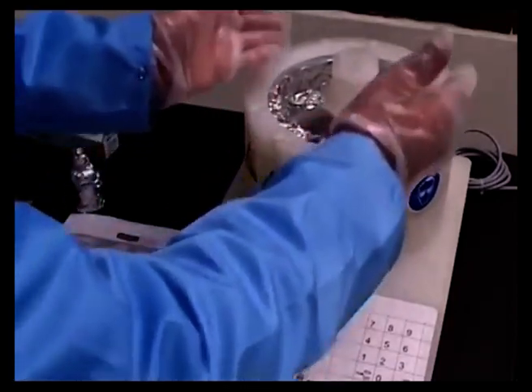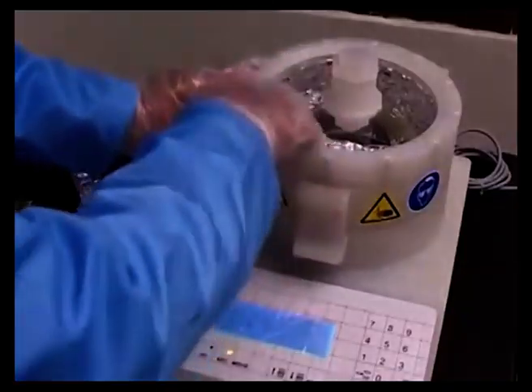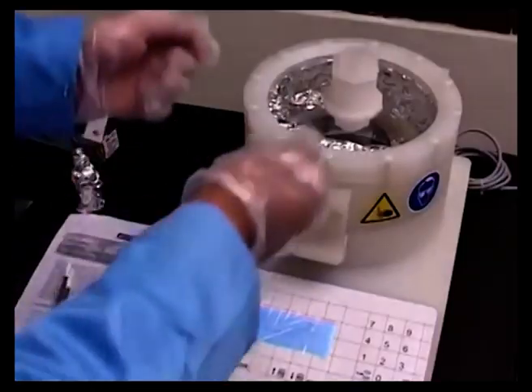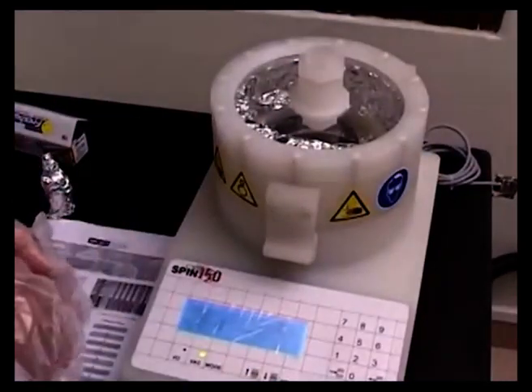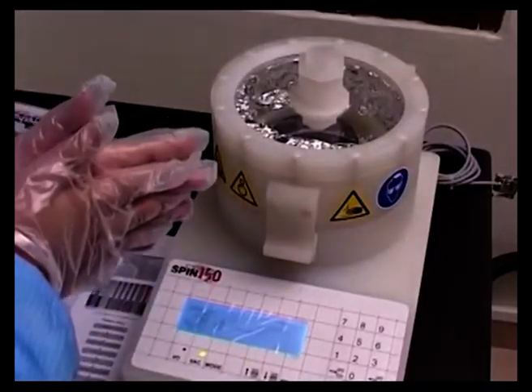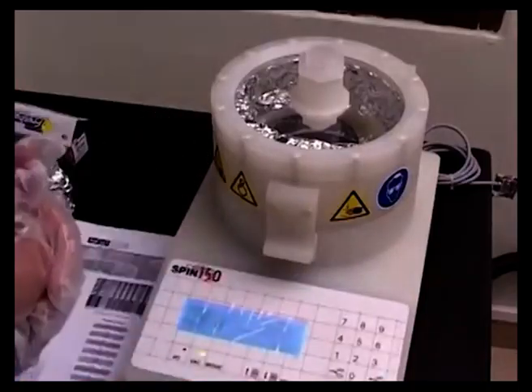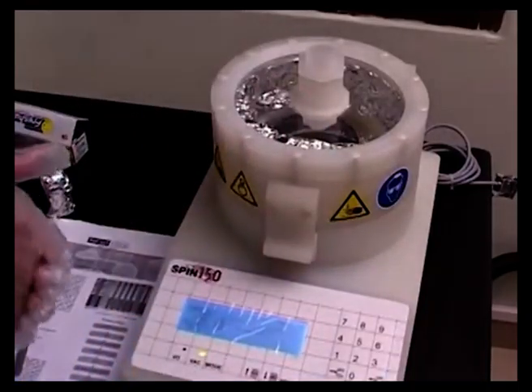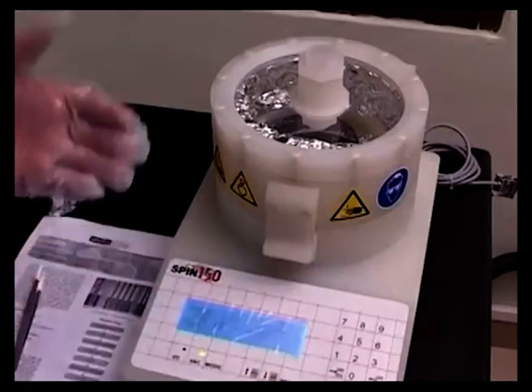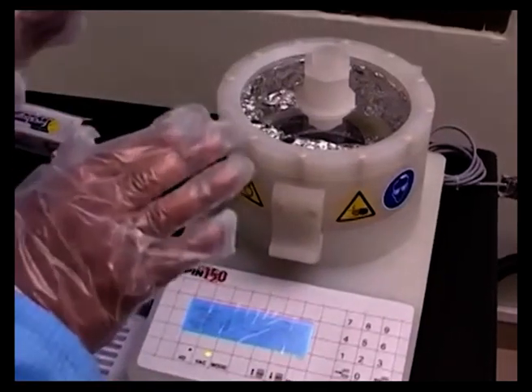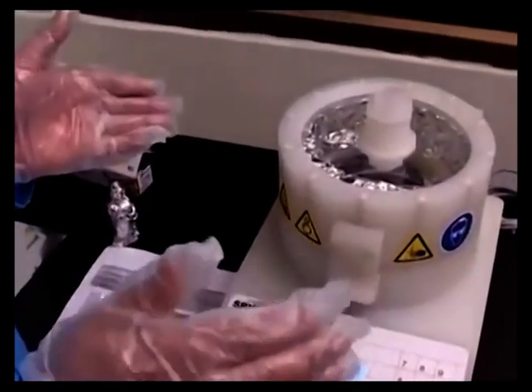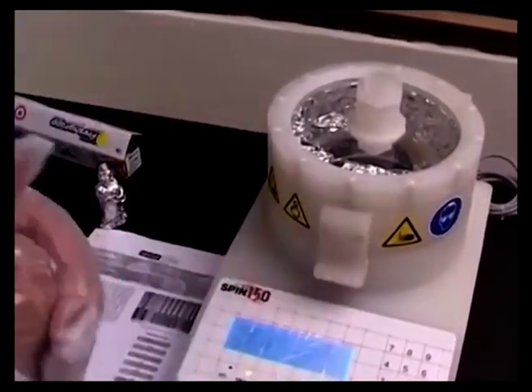So now it is almost ready to rotate and spin and coat whatever is there on the surface of the material. We would also like to check whether this wafer has been centered, and the best way to do that is to close the lid and see from this transparent section on the top whether the wafer is really at the center of the spin table. In case it is not, you can switch off the vacuum and change the position so that the wafer comes to the center of the spin table. We are ensuring that there is no wobble of the wafer, and that it rotates on its own axis, which ensures that there is no underutilization of the resist at the very center of the wafer.